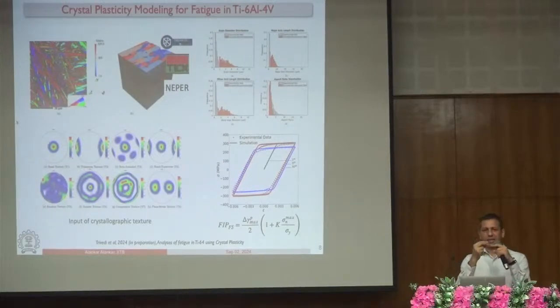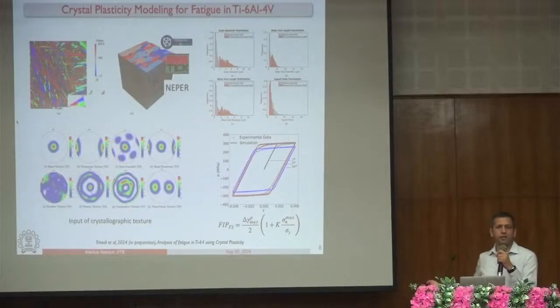So think about that material if it is made in the form of, let's say, a dog bone shaped specimen and given multiple cycles, and let's say it fails, whatever happened to that material must have happened at the first cycle as well. Some part of that must have happened at the first cycle, right? That is the methodology that we are applying. It's not something new, it has been there in the literature, but we are going a step forward that rather than running just 3 cycles of the simulation, which is able to capture this fatigue indicator parameter, meaning a parameter that will be able to tell you how much fatigue will happen or whether the material will fail or not, right? Even beyond this FIP, fatigue indicator parameters, we are applying machine learning also, right? Now, let me restate this that we are actually not running 50,000 cycles. We are running 3, 5, maybe 50 cycles.